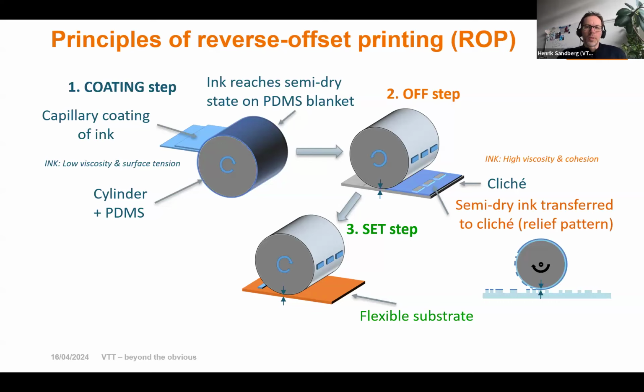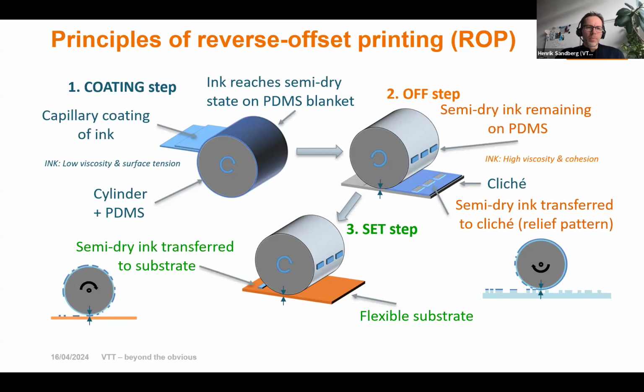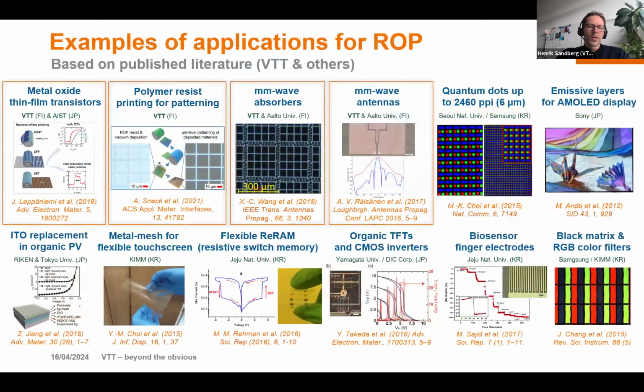So the ink you want to remove in the off step is left on the cliché, so the cliché has to be cleaned before the next process. Then you have the ink still on the PDMS, still in a semi-dry state, so that it can be transferred onto the substrate. And this is where you just press the cylinder onto the flexible film, and it will transfer due to the interaction between the PDMS and the ink, and the ink and the substrate. So that's in general how the process works, and you can do a lot of things then with